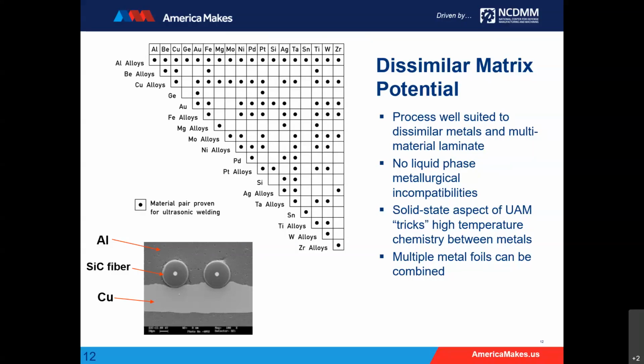As far as difficulty, the higher the yield strength, the more difficult it is going to be to weld the material with this ultrasonic process. So that's always a consideration. Typically, the higher the yield strength, the thinner the layers, in order to accommodate that disparity in strength.